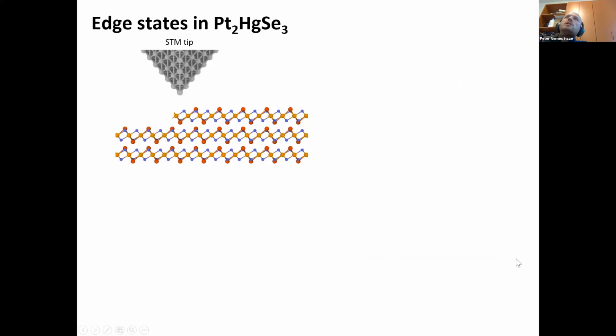Now, of course, this material should host some edge states, and in the case of many other 2D topological systems, like tungsten telluride, like bismuth rhodium iodide, like the transition metal dichalcogenides, usually the top layer of the material behaves quite similarly to the monolayer. So this encourages us to just look at the edges or monolayer step edges on top of the bulk crystal and try to find the edge states.